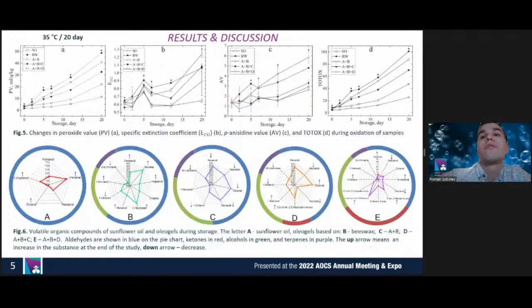When testing hypothesis two, we found that the sample of sunflower oil, according to all methods of evaluation, showed itself to be more stable in oxidation. The oleogel based on hydrocarbons and monoesters turned out to be more stable. The main volatile organic compounds of the samples are aldehydes, ketones, and to a lesser extent, alcohols and terpenes. Note that the terpene limonene was found in the oleogels, which can affect the result of an anisidine value measurement.